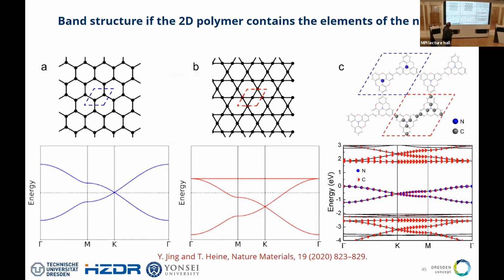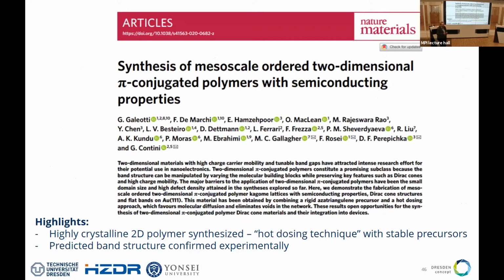So then just last year, we were asked to explain that a little bit more in detail, and we really showed here, I mean, here you have the honeycomb lattice, and here you have the Kagome lattice. But here you have the very simple tight binding band structure, and here you have the two-dimensional polymer. I'm just highlighting here the honeycomb elements and the Kagome elements, and that here is a fat band calculation showing the projection, and you can really see that those two lattices are reflected in this real polymer band structure. And then it has been made. So I was very happy. Also, there was this paper last year where they have a new technique, this hot dosing technique for making these monolayers of these two-dimensional polymers. And they were confirming both the Dirac bands and the flat bands experimentally. So we were very happy about that.